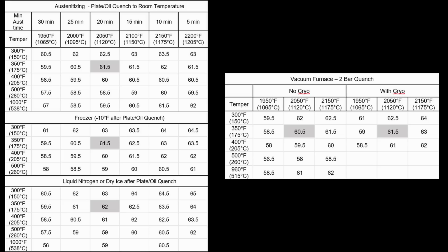For the MagnaCut datasheet, I measured hardness for a whole range of austenitizing and tempering combinations with plate quenching, and I did that with no cryo, a household freezer, and also with liquid nitrogen. We also sent steel to Peters Heat Treating, which has typical factory vacuum furnaces that use a pressurized gas quench. They used a 2-bar nitrogen gas quench. You can see that the hardness after the pressurized gas quench by Peters is typically 0.5 to 1 Rockwell C lower than when I plate quenched individual pieces.